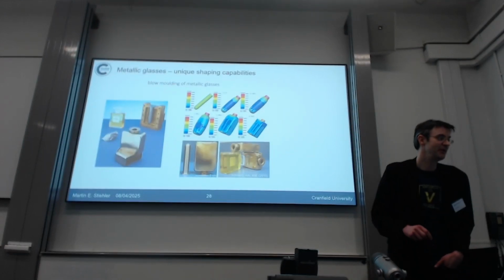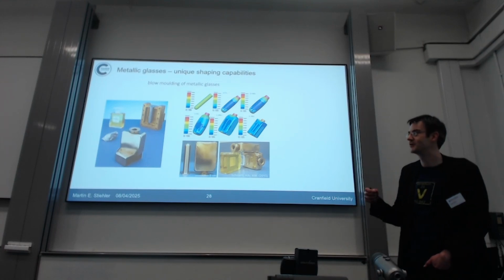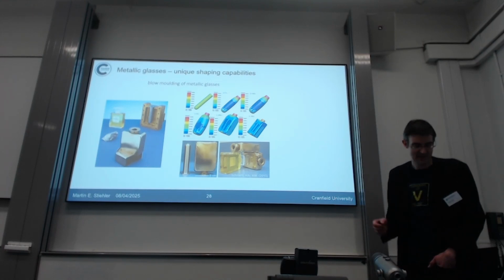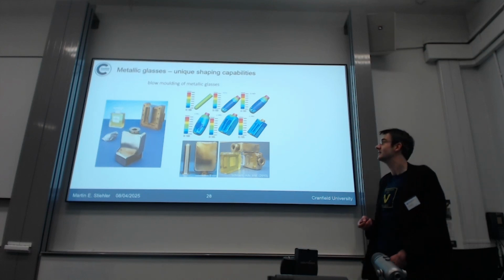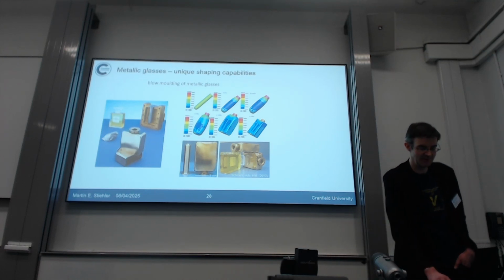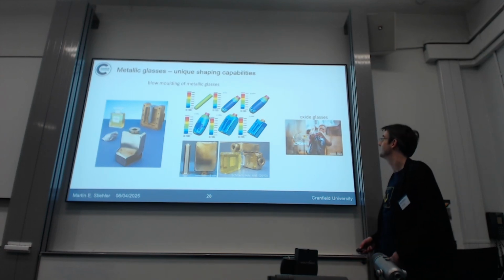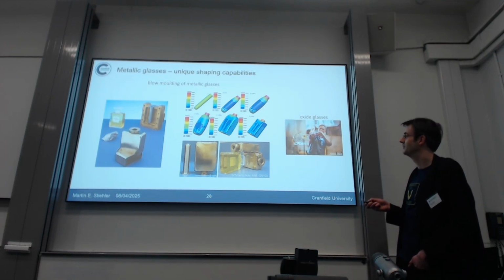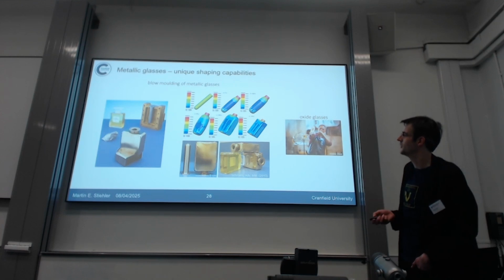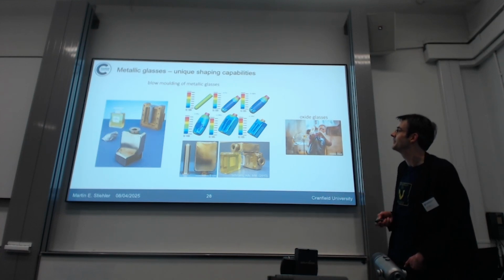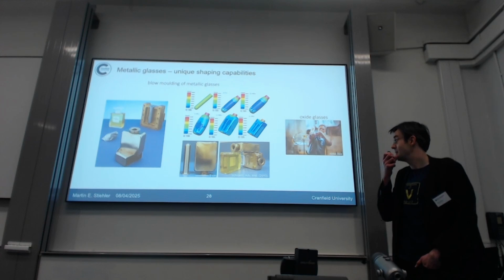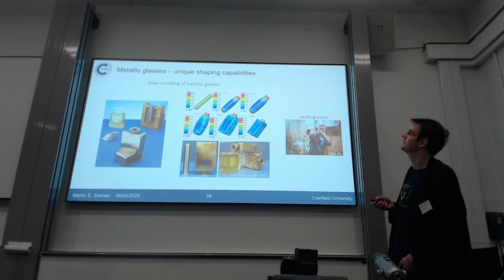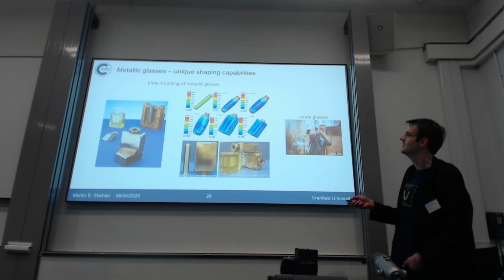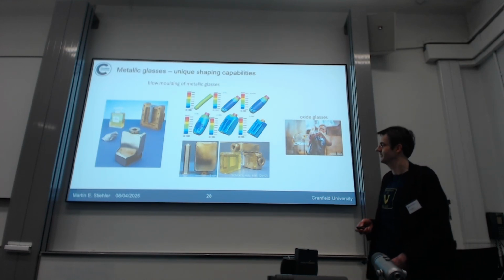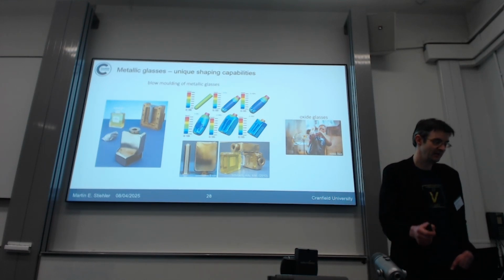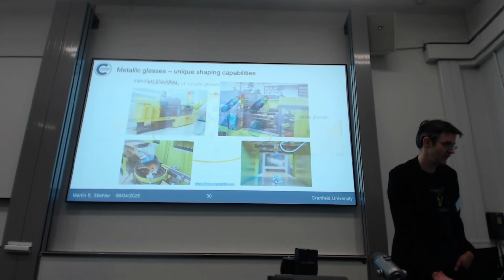There's something else you can do with metallic glasses, which you cannot do with normal crystalline materials, and this is somehow comparable to the traditional oxide glasses. You can do blow molding, right? So you know blow molding probably with oxide glasses, and you can do the same thing with metallic glasses. You start with a simple rod-like thing, put it in a die, heat it up above a special temperature I will talk about in a second, and then you can form that, and then you let it cool down, and you end up with a nice shape there. And I think you can also imagine a lot of applications for that.